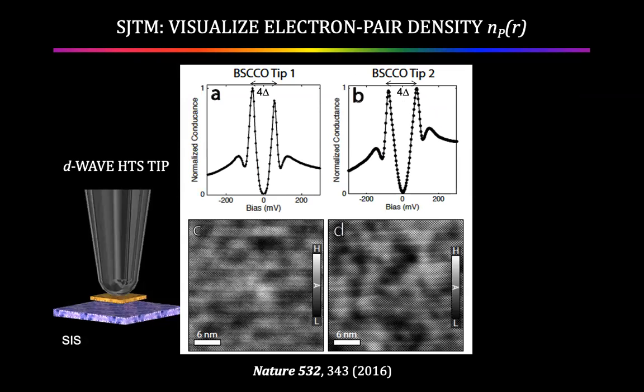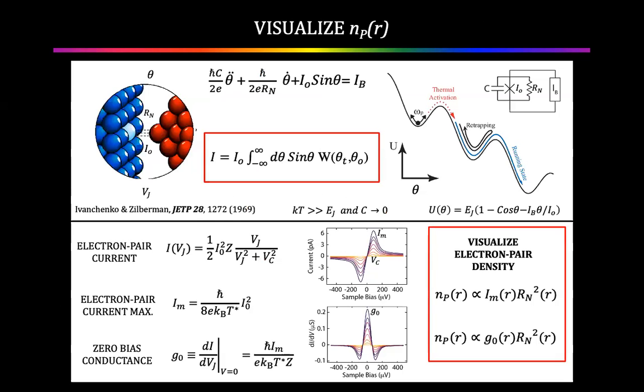Okay. All right. So for a long time, that was not a doable project. Dynes had introduced these ideas at 4 Kelvin, even at junction resistances of, say, 50 kilo ohms. He couldn't make an image because although he could detect this signal at 50 kilo ohms, the tip is already poking into the surface. So he couldn't move it around and make an image.